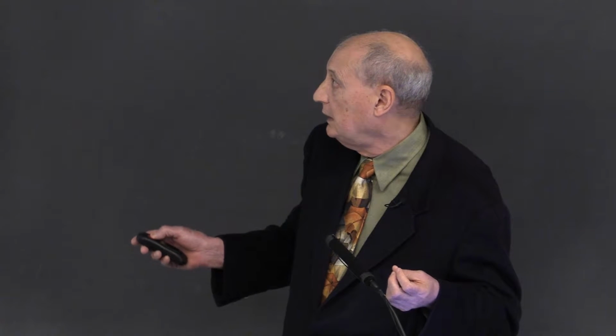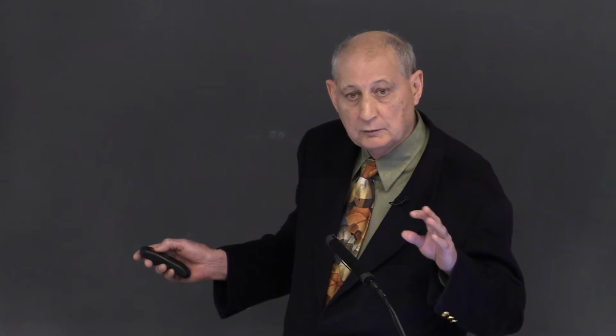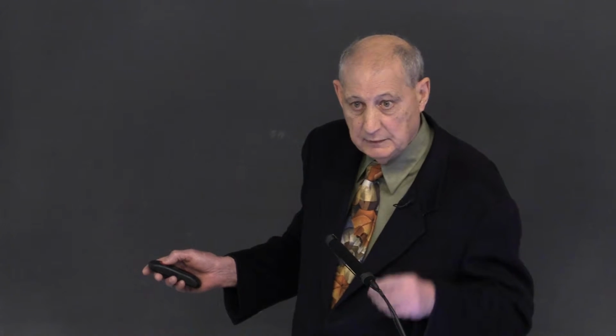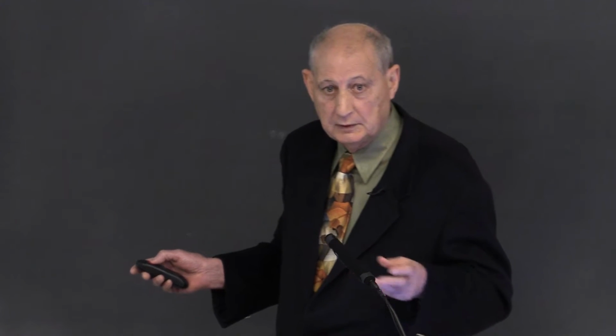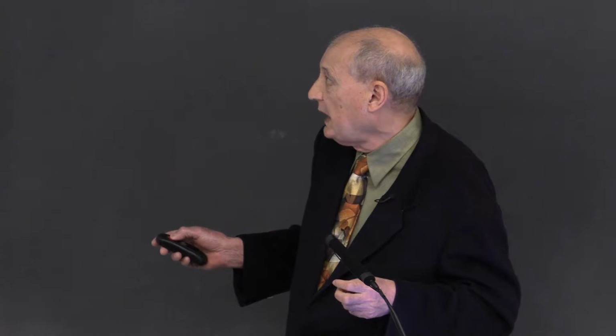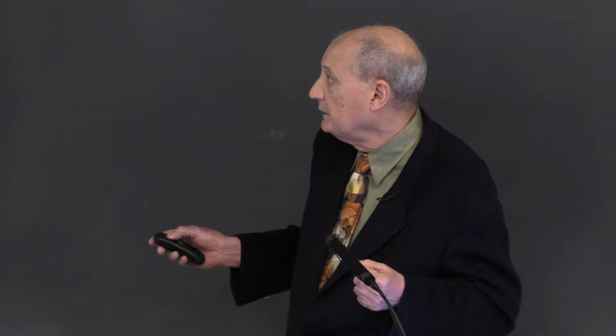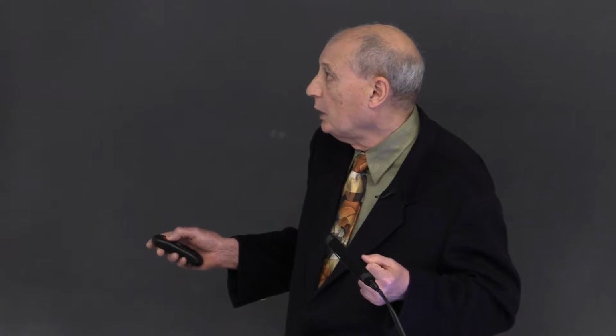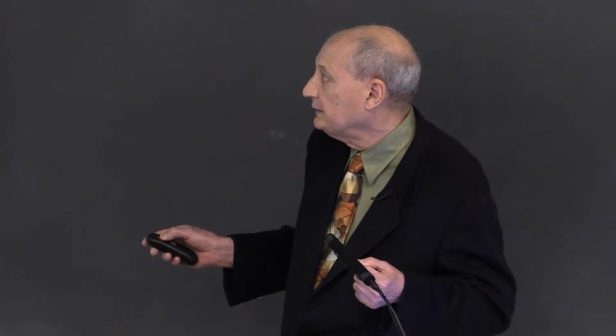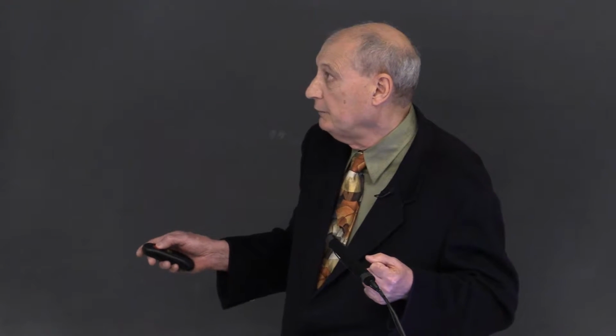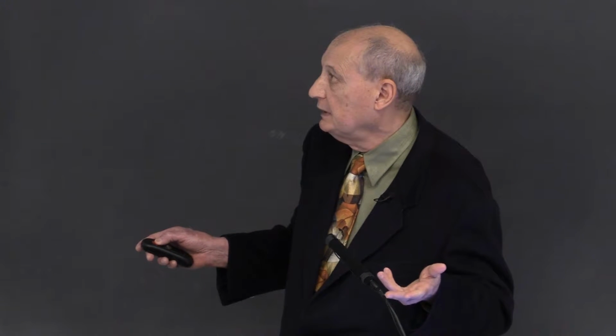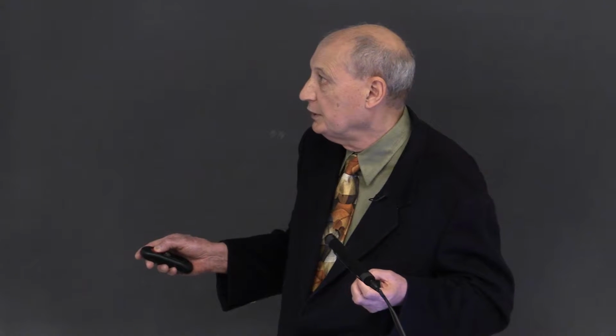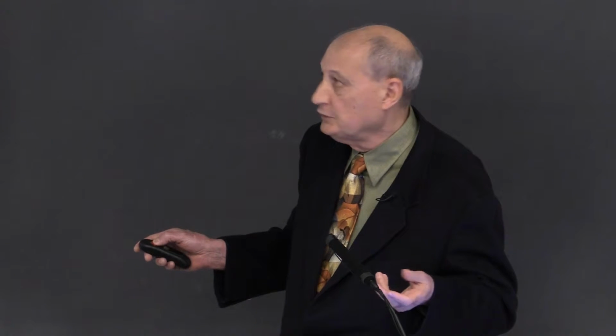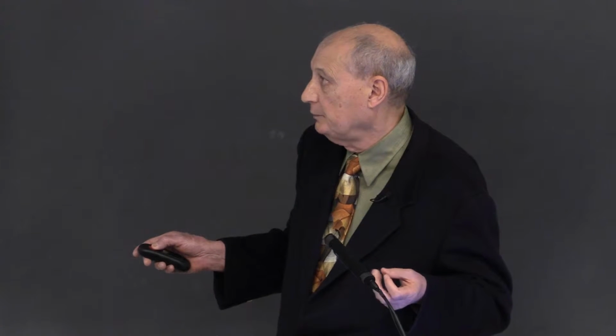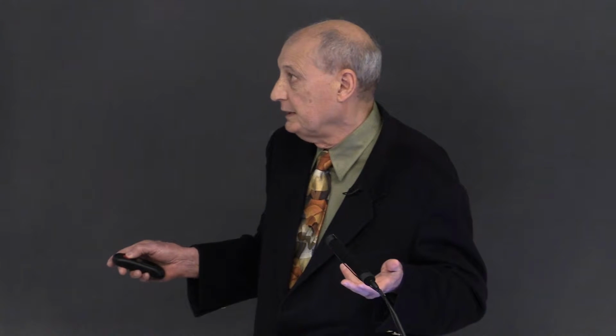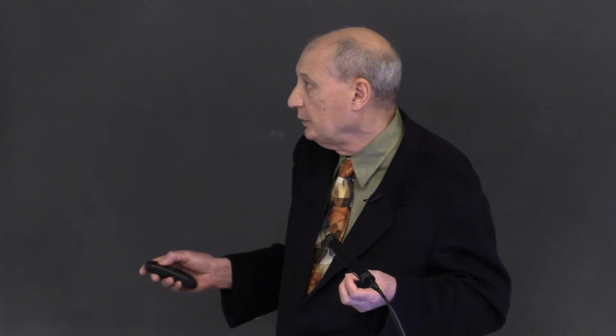And this accounts for the delay. One of the triumphs that was effected by Bruce Robinson and his students and by my students was that of developing a theoretical understanding of why we got this effect even for chromophores that were relatively dilute, for low number density materials, such as found by dissolving a chromophore in a polymer to create a composite material or covalently attaching that chromophore to a polymer backbone.